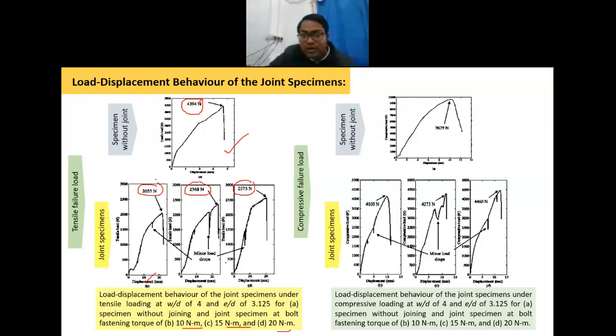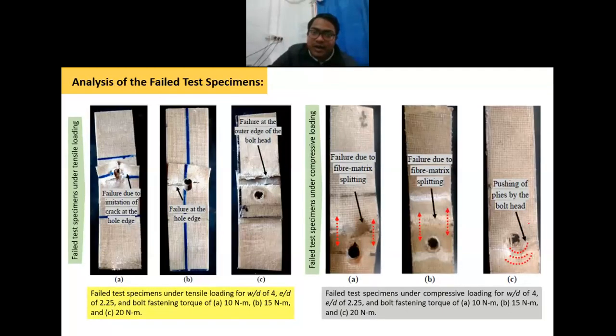So by increasing the bolt fastening torque, you can improve the joint strength or joint efficiency. And a similar observation we have made for the compressive failure load also. For more bolt fastening torque, you have more compressive failure load. So this is the analysis that we have done, and finally we analyzed the failure of these joint specimens. We have observed different types of failure under tensile loading as well as compression loading.